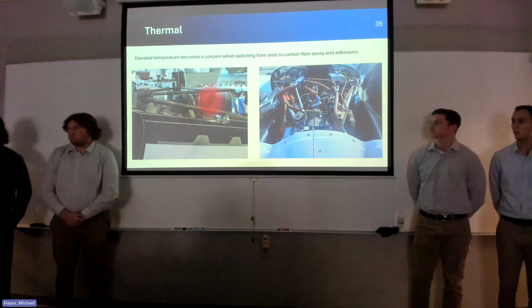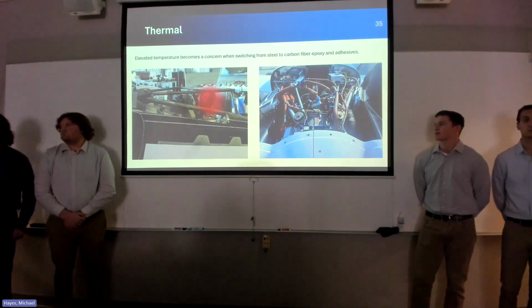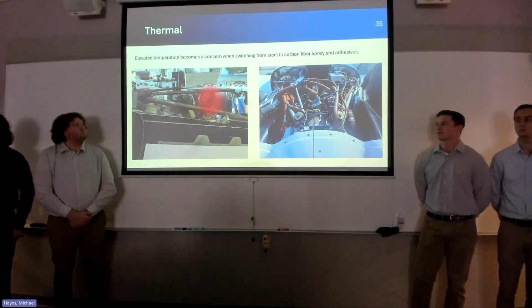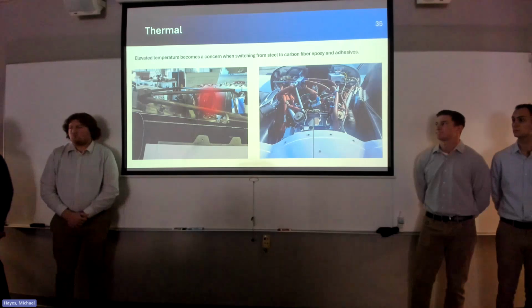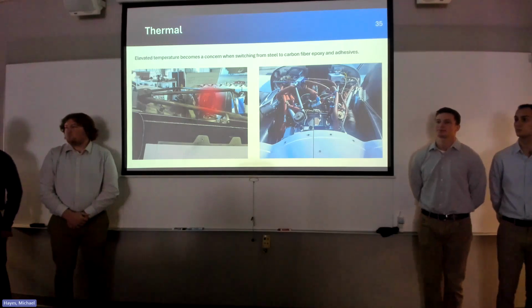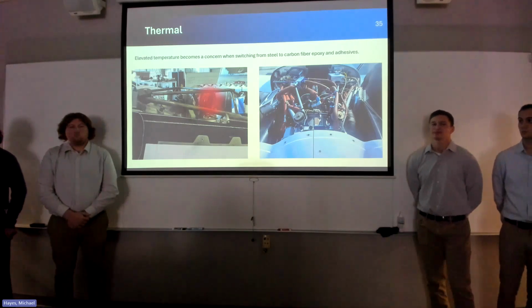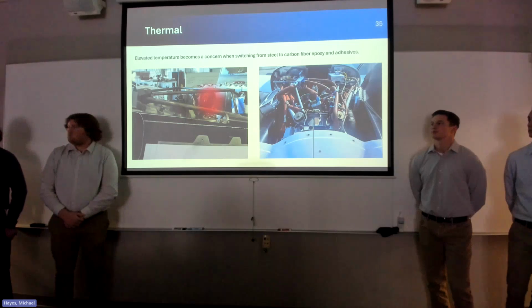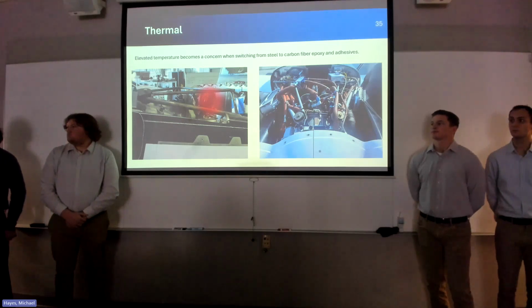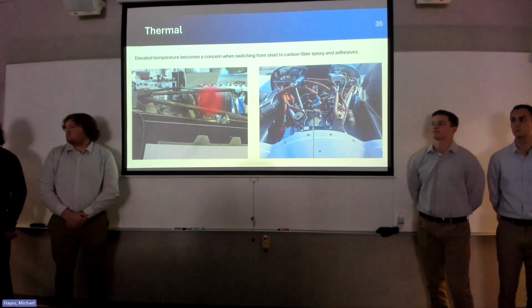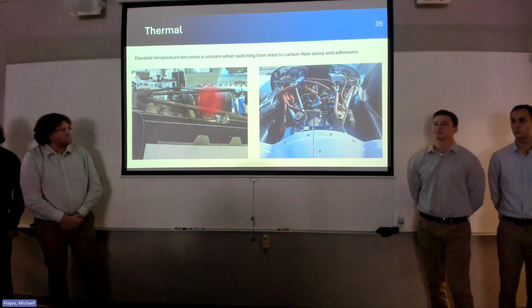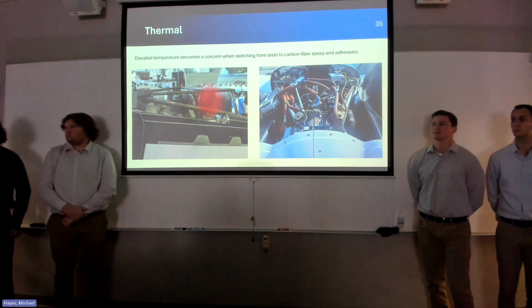All right, so similar to how we had to relook at joinery, we also had to relook at thermal effects. And there are 2 main considerations. The left picture shows the engine bay with the turbo highlighted in red, which will get up to a temperature of around 1400 degrees Fahrenheit, which is far above the maximum temperature of the epoxy used in the carbon fiber, which is only up to 350. So any member near that turbo will need to be insulated.